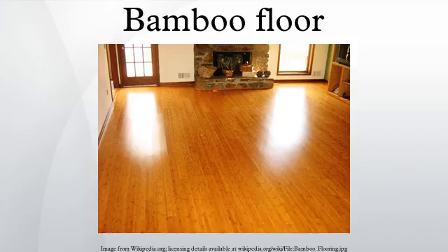Bamboo floor manufacturers and sellers promote its strength, durability, its eco-friendliness and its natural resistance to insects and moisture. The hardness of traditional bamboo flooring ranges from 1180 to around 1380, while newer manufacturing techniques including strand-woven bamboo flooring range from 3000 to over 5000 using the Janka hardness test. Other flooring materials have comparable Janka ratings, with a higher number indicating a harder material: red oak, white oak, rock maple, hickory, and Brazilian cherry/jatoba.